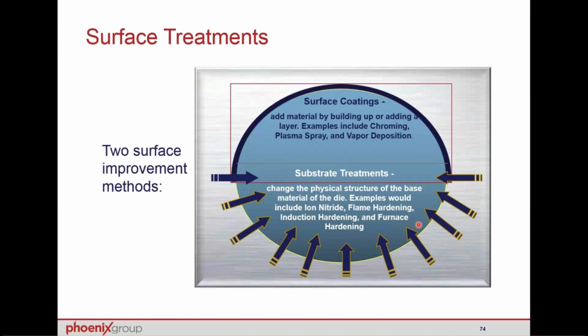With the new lower quality cast irons and cheaper cast irons that are being utilized, they don't flame harden or heat harden in a consistent manner. So they've come up with this thing called ion nitriding. Basically, it's done through a furnace. The die is put into a furnace. The die, I believe, is charged negatively. The atmosphere is charged positively. All of the oxygen is evacuated from the chamber, and pure nitrogen is put into the chamber so as to prevent rusting. As the current increases, the nitrogen becomes electrically excited, bombards the surface of the die, and actually creates an iron nitrogen alloy.